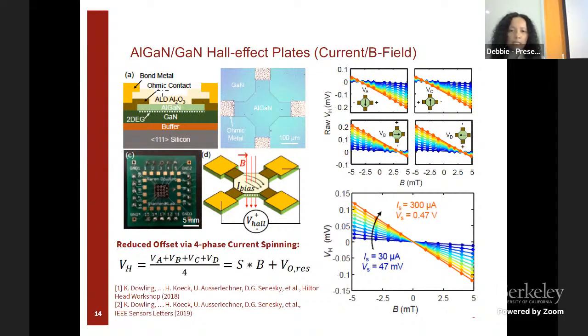So using this fabrication process, you can start to make different types of transducers. This is one that we've matured over the years. So using the AlGaN/GaN heterostructure to create magnetic field sensors through the Hall effect. So instead of a silicon doped junction, you have now your two-dimensional electron gas as your conductive layer, ohmic contacts here, and this is your Hall plate. So if you expose this to a magnetic field and you induce a current across two sets of electrodes, the magnetic field will bend the trajectory of the electrons, and you can measure that off with a secondary set of electrodes.